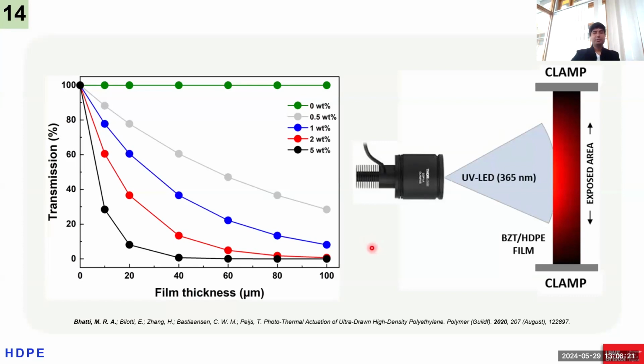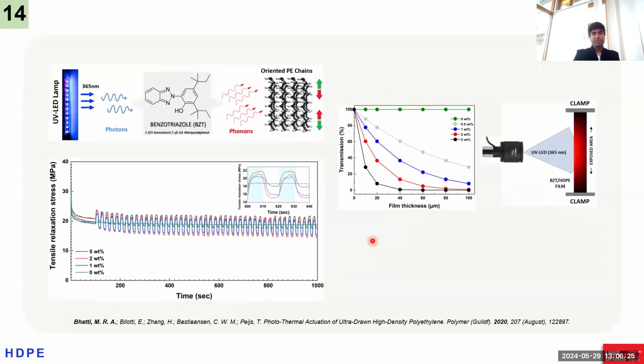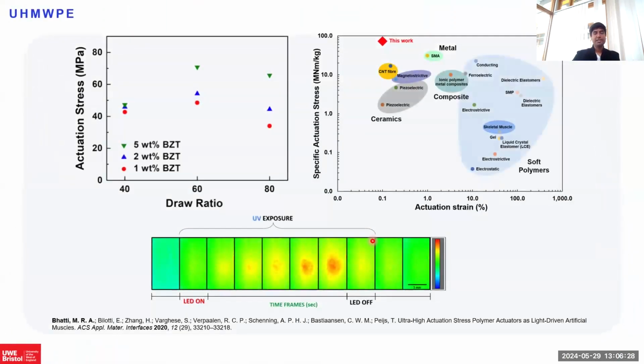So we thought of using another material, ultra-high molecular weight polyethylene, but the process is different. It is not processed by melt processing because of the high molecular weight. We used a gel casting process in which ultra-high molecular weight polyethylene powder is mixed with xylene, a solvent, and then BZT is added to that, and then it is gel casted into a sheet, dried, and then drawn later on to get a high draw ratio. Using ultra-high molecular weight polyethylene, we were able to create different draw ratios of 40, 60, and 80.